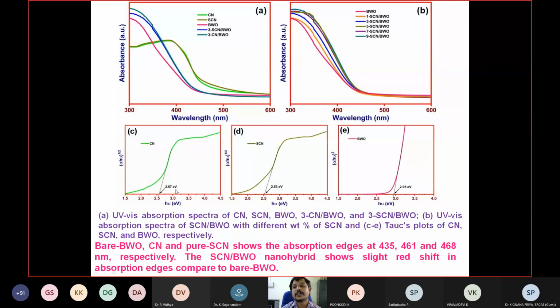Then we studied the optical property. The optical property reveals visible light absorption. Then we calculated the band gap using the Tauc plot method for the bare carbon nitride, sulfur-doped graphitic carbon nitride, and bare bismuth tungstate. Why? Because these values will be used to propose the mechanism.